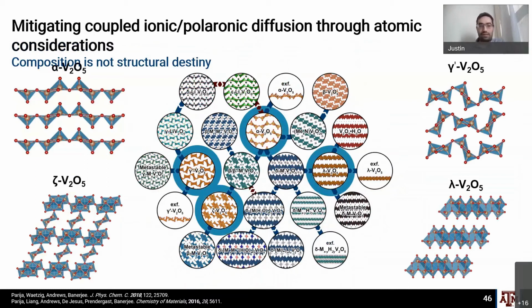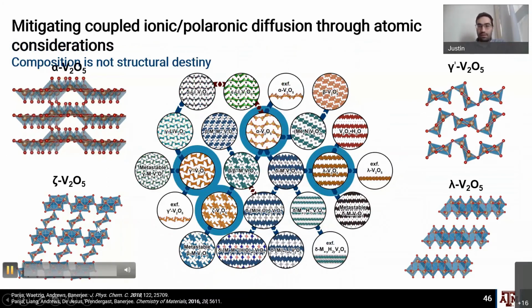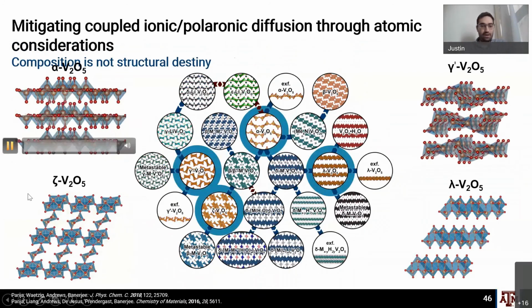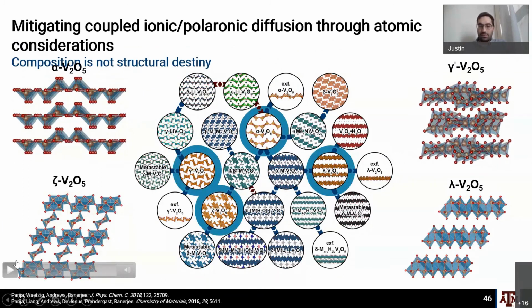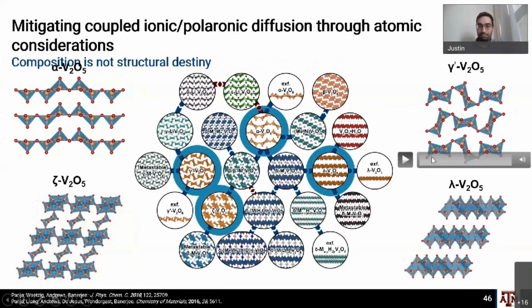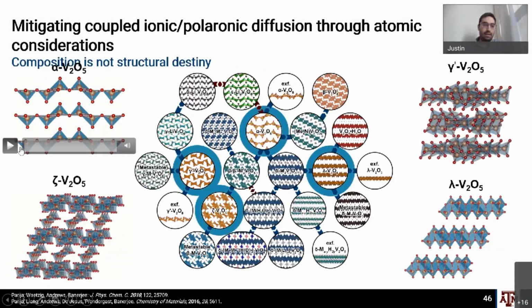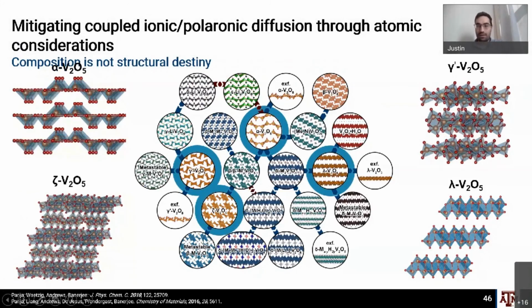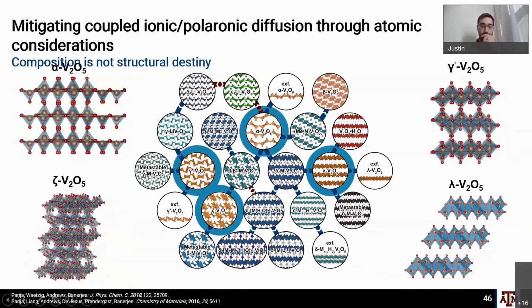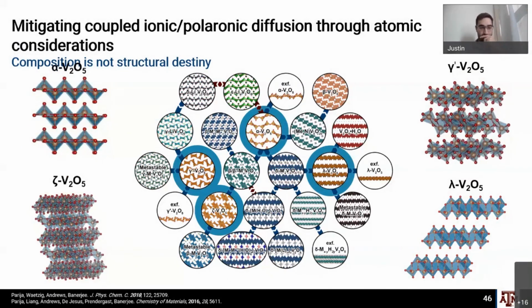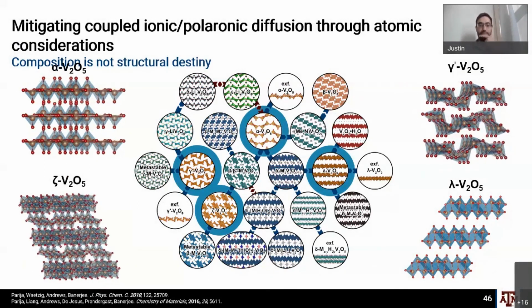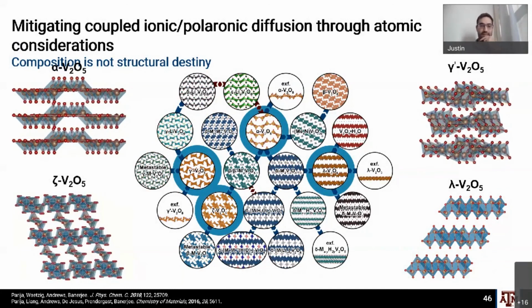So to highlight a few of these, there are a lot of ternary phases in here, but just 4 polymorphs that we've been able to work with extensively. This is alpha V2O5 at the top left. I'm just going to play some of these videos here. It's going to be a little bit noisy maybe, but just so you can see how these things vary. What this does is it allows us to have a totally different structure and bonding, different diffusion pathways, and also different density of states in terms of the way that the vanadium and oxygen hybridize to give us different states that we access as we lithiate these things.